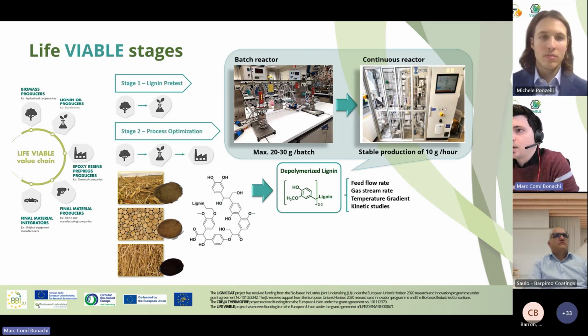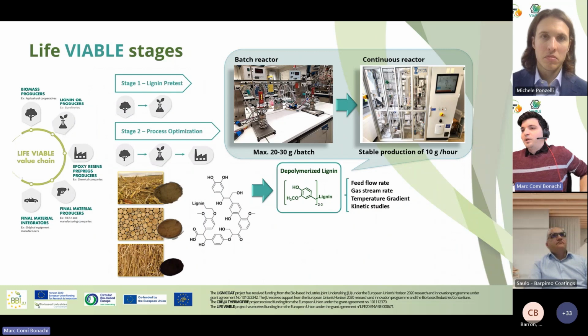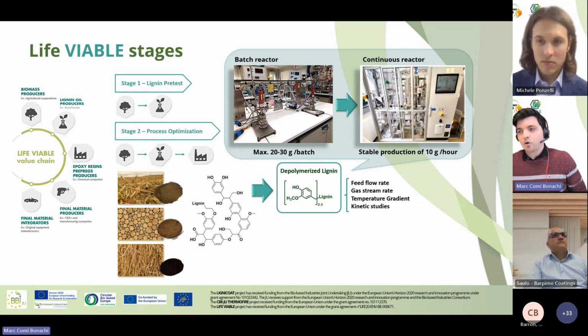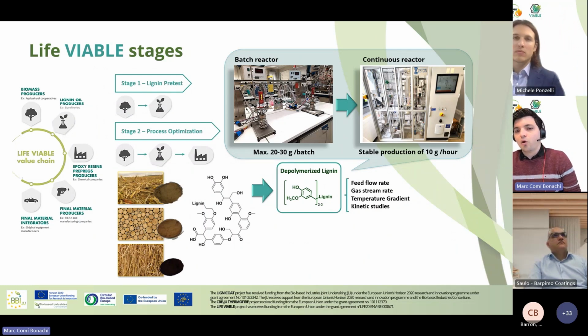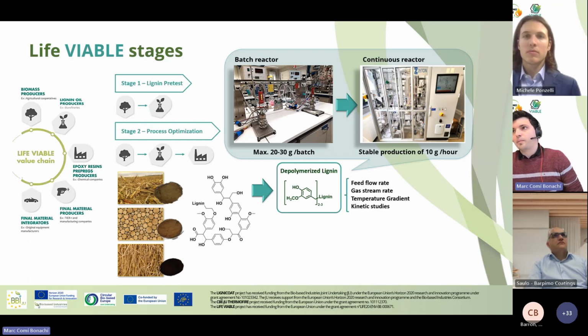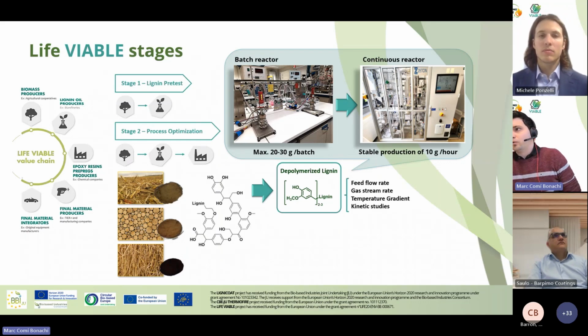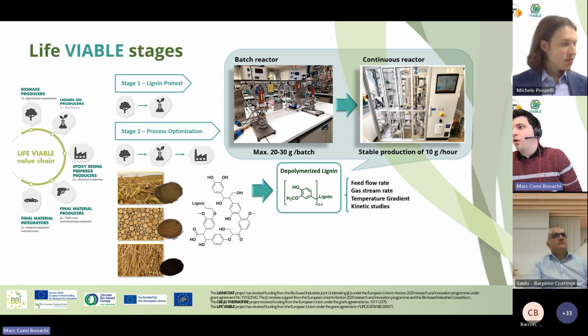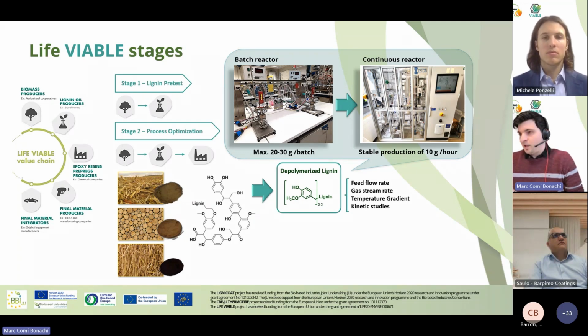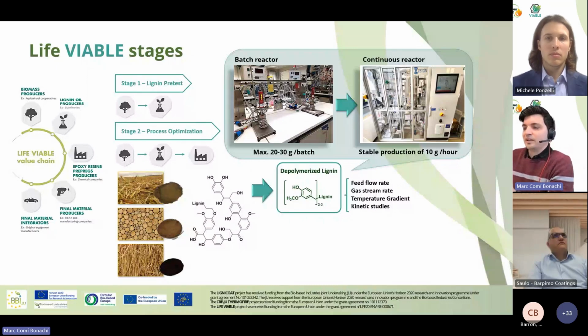So for the second stage of the project, process optimization, what we tried is, with the rest of the lignins, to go bigger. Not only go bigger, go more continuous. We passed from a batch reactor at lab scale, producing 20 to 30 grams per batch, to a stable production over different hours of 10 grams per hour. This allowed us to treat this lignin, solubilize it, and then put it in the continuous reactor.